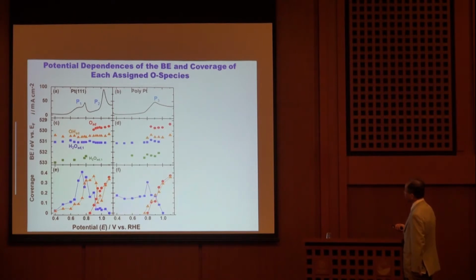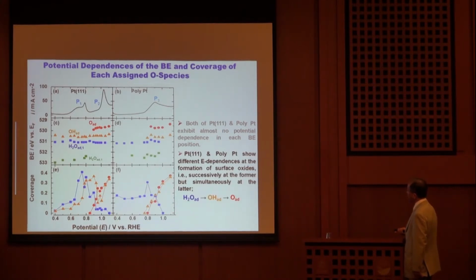On the polycrystalline electrode, not only the single crystal but also the polycrystalline exhibit almost no potential dependence in each binding position. And platinum 111 and polyplatinum show different potential dependencies at the formation of the surface oxide, that is, successively at the former, but simultaneously at the latter. So, a different phenomenon.